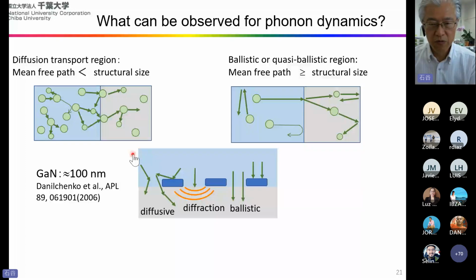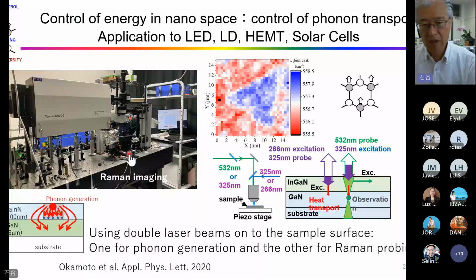And what happens in the crystal, we are now researching, and how to measure the phonon transport is a very important topic. In my laboratory, I have introduced a spatial Raman imaging system using double laser lines simultaneously incident on the sample. For the UV light, the heating energy is fabricated, and by using another laser, the heating condition in the underlayer is observed. By this measurement, we can discuss the energy transport across the heterointerface. In the multilayer structure of devices, the heat phonon transport across the heterostructure is very, very important.